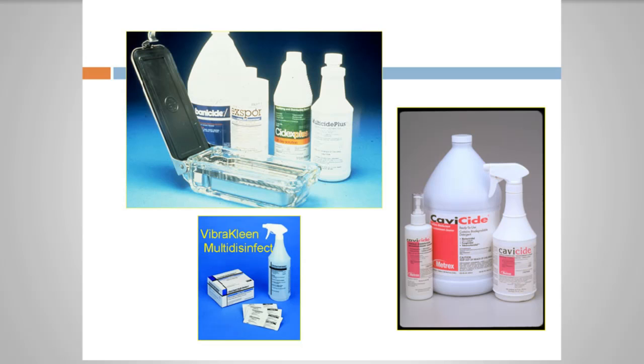And then we come to disinfecting of our impression material. Now, if you have a problem with tight-fitting crowns or open margins, it may not be your technique at all. It may be the disinfecting. What we found out from the laboratory, and I've changed my whole sequence of events now just based upon that, is that you would disinfect it, it would then go to the laboratory, and then they would disinfect it. So I would disinfect with brand X, and then they would disinfect with something else. That could have some effects on the impression material. So just be careful, talk with your laboratory, find out what they're disinfecting with, because it can definitely have an effect.